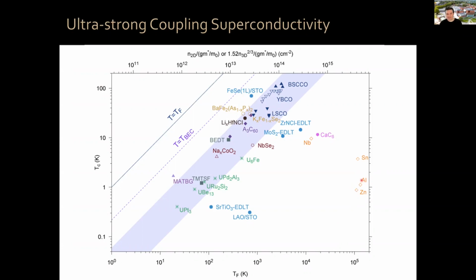Aluminum, for example, has a TC of about 1 Kelvin and a gigantic electron density. So it superconducts very modestly. As you go towards this diagonal, you see typically more and more exotic types of superconductors. In particular, all the unconventional superconductors are in this purple band, okay? Magic angle twisted bilayer graphene, when we were reporting TC's at 50% normal state resistance, was here, very strongly coupled, okay? Now, this is the TBKT over TF of 0.25, okay, that I mentioned, for the BCS-BEC crossover limit in 2 dimensions.